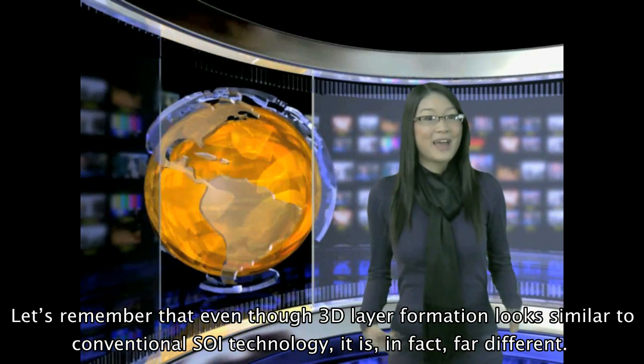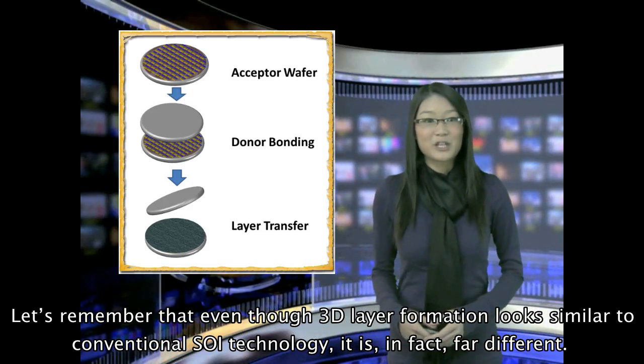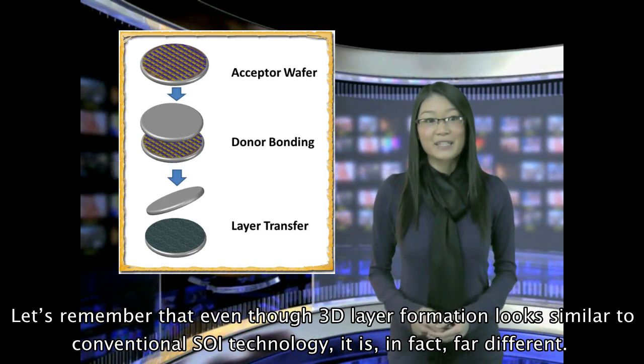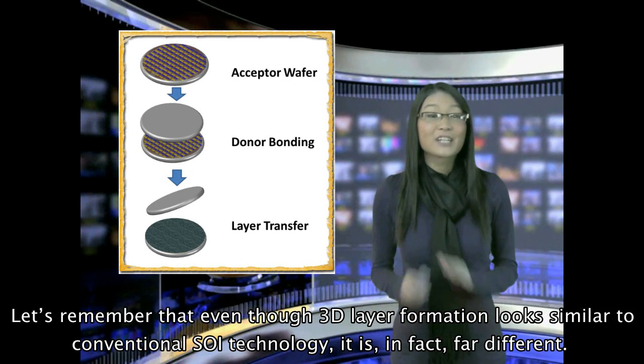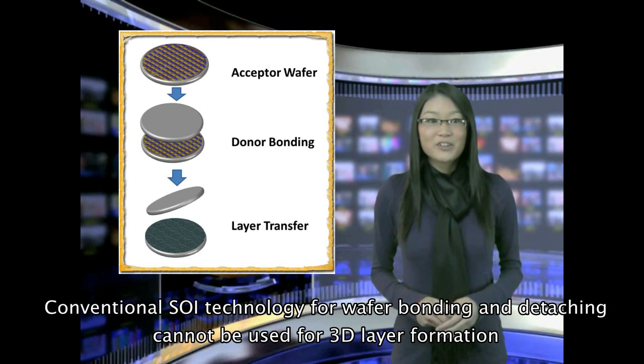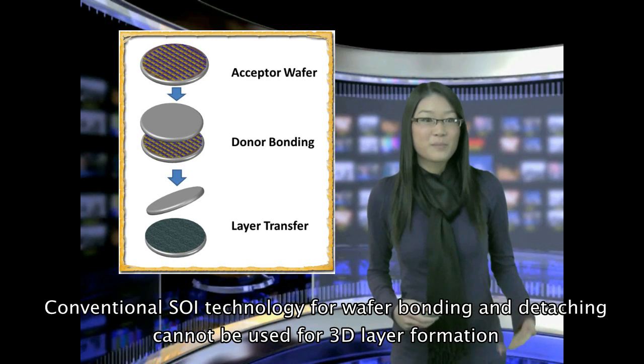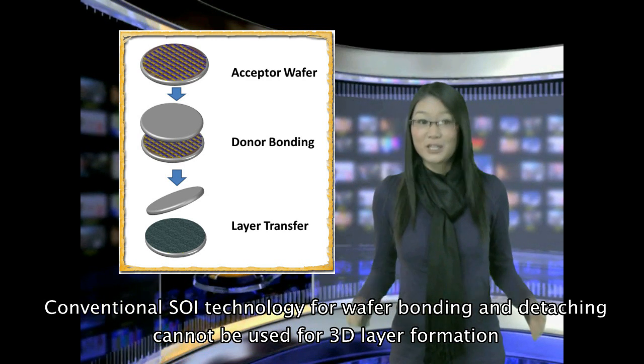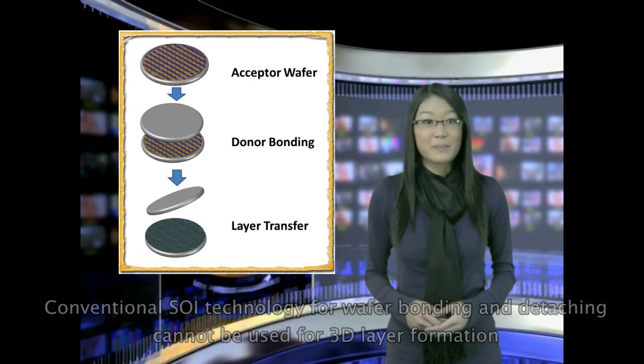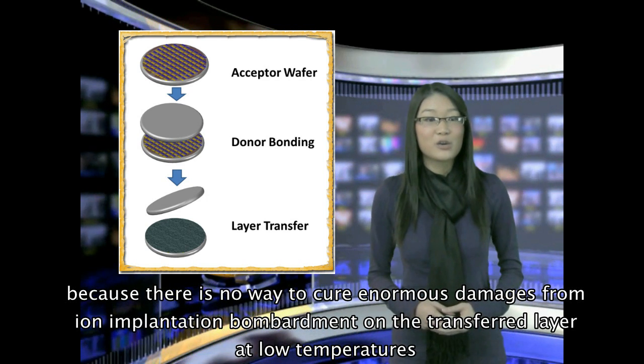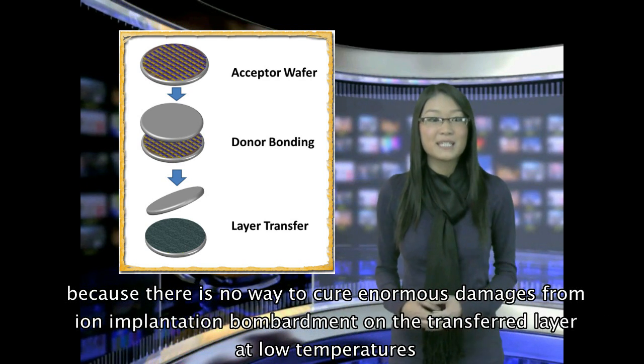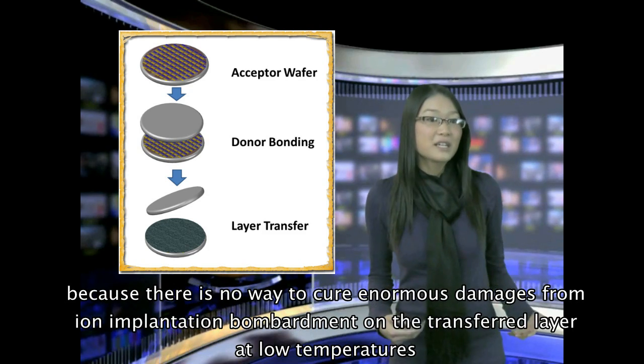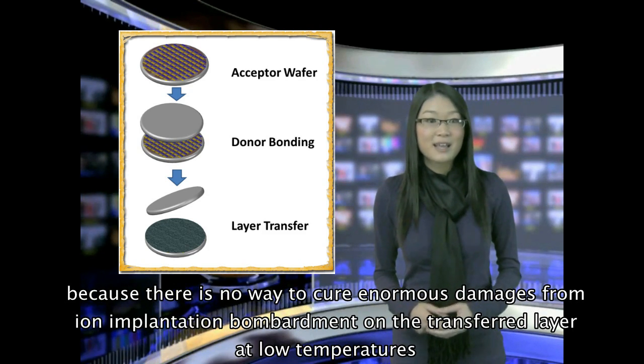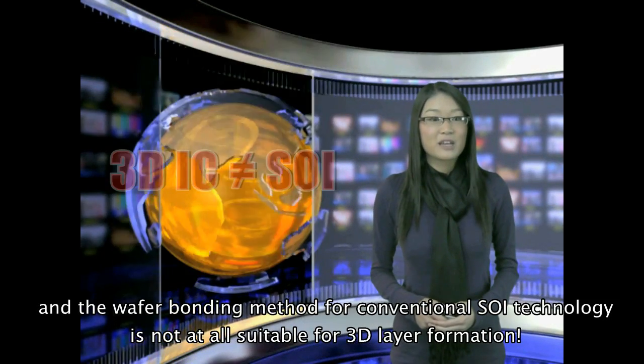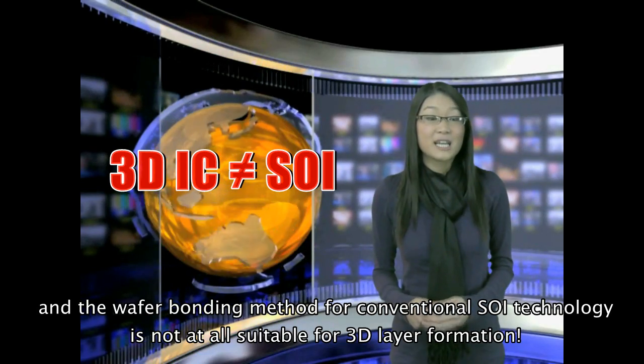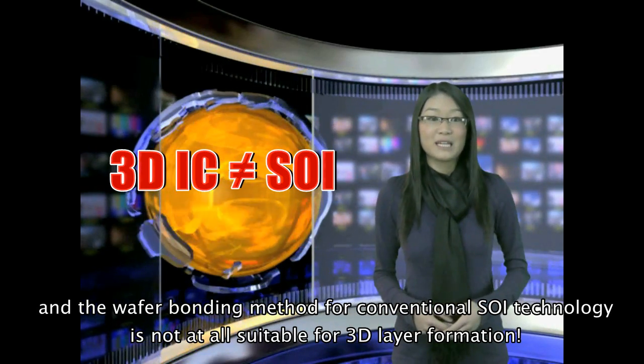Let's remember that even though 3D layer formation looks similar to conventional SOI technology, it is in fact far different. Conventional SOI technology for wafer bonding and detaching cannot be used for 3D layer formation because there's no way to cure enormous damages from ion implantation bombardment on the transferred layer at low temperatures. And the wafer bonding method for conventional SOI technology is not at all suitable for 3D layer formation.